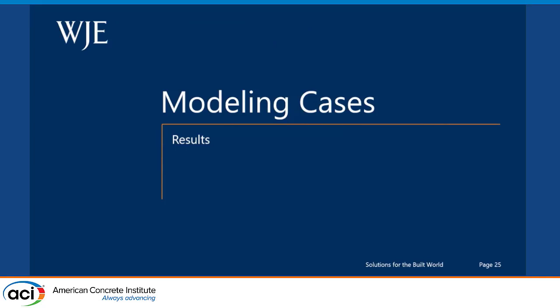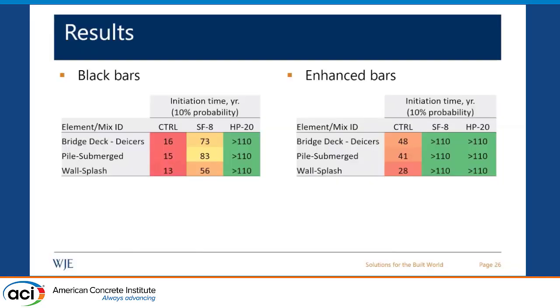So, getting into the modeling results. Here I'm showing color-coded tables that show the time until you get to 10% probability of corrosion initiation. The table on the left shows the cases with black bars, and on the right, the enhanced bar. And we looked at what the results would be using the different mixes and the different cases here. These results are based on the inputs that we are given. So we considered the aging factor based on the electrical conductivity testing. We considered the chloride thresholds that are given.